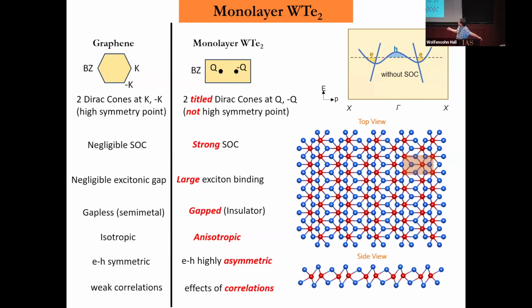In graphene, we know the Brillouin zone is hexagonal and it has K and minus K points. Interesting physics happens at these two high symmetry points. And what's most interesting, of course, is the Dirac cone, and then you can engineer the Dirac cone. This is a linear band, and the linear cone really exists up to 1 eV, something like that. We also have two Dirac cones in monolayer tungsten ditelluride. It does not happen at a high symmetry point like K or minus K. It happens at this Q and minus Q.